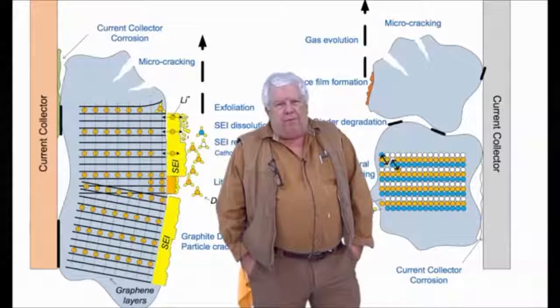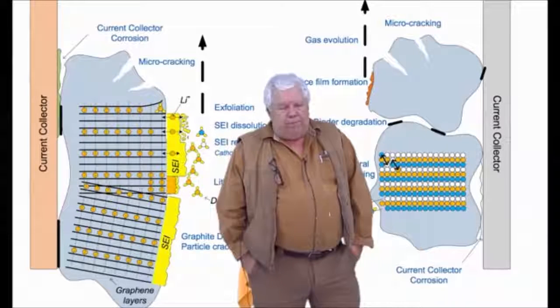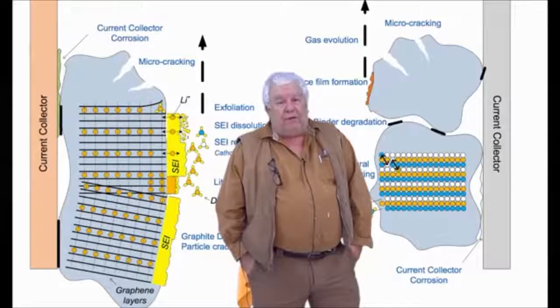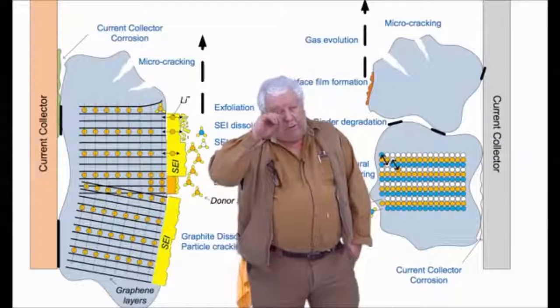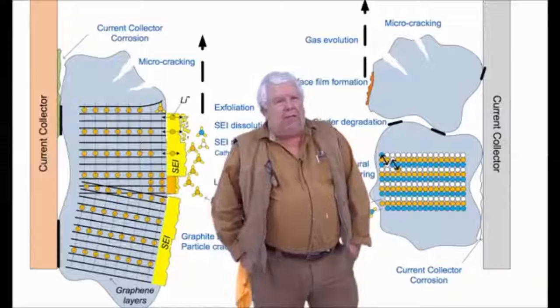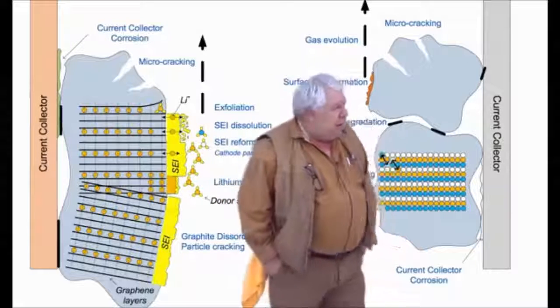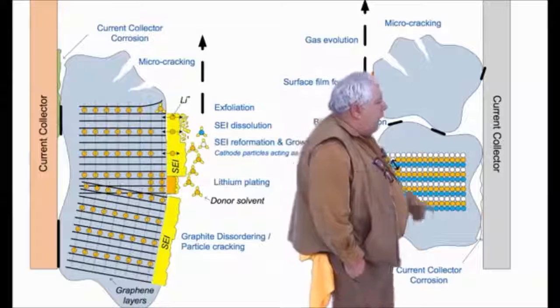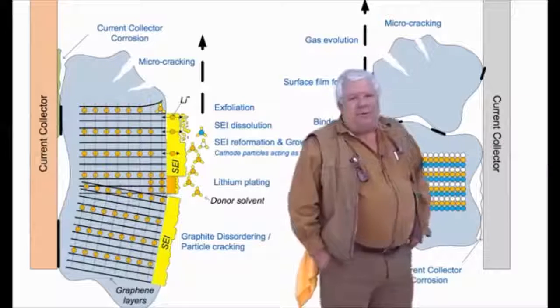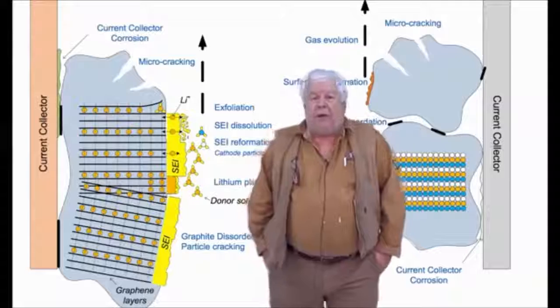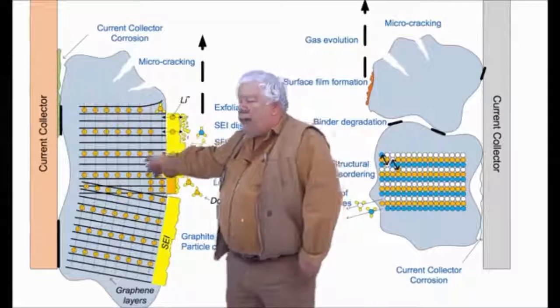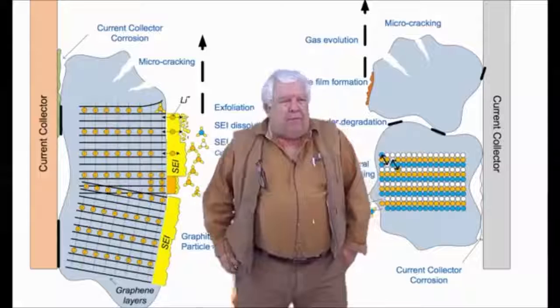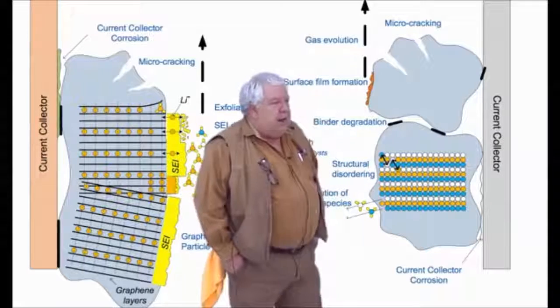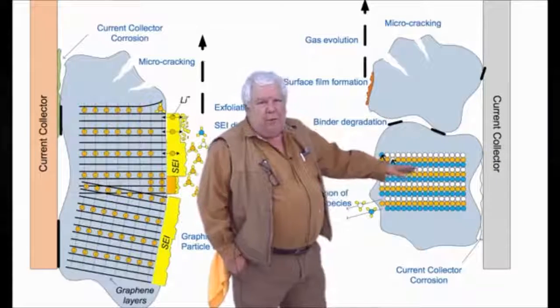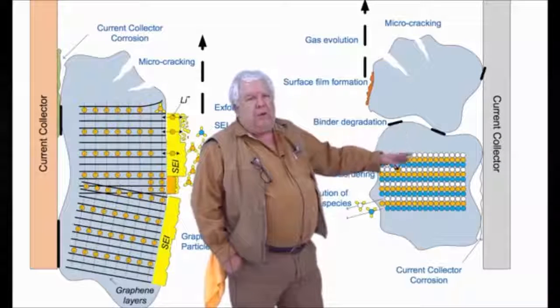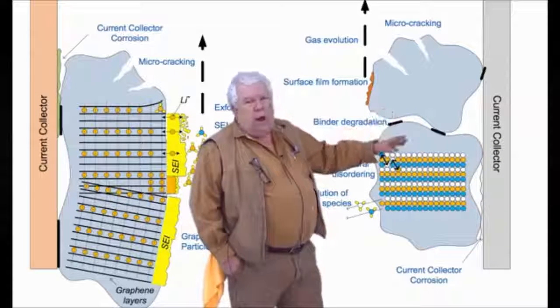Why do I like lithium iron phosphate so well? Well, because it's at 250 degrees centigrade and up to about 400 degrees centigrade, and it's not really a lot of oxygen that it releases. In the case of lithium cobalt oxide, it's a lot of oxygen, and it starts to go at 130 degrees centigrade, which is back here where we're melting our SEI layer, at between 130 and 150 degrees centigrade. So a much lower temperature will cause free oxygen in a lithium cobalt oxide cell, and that's why they burn.